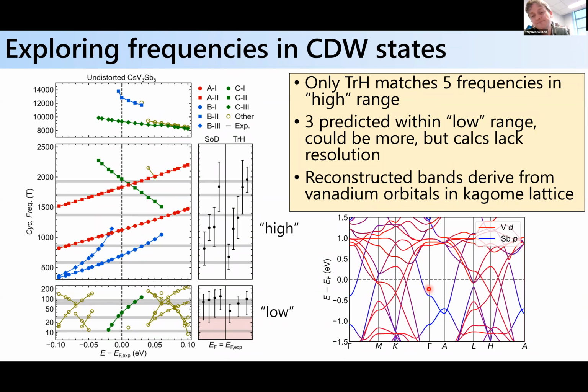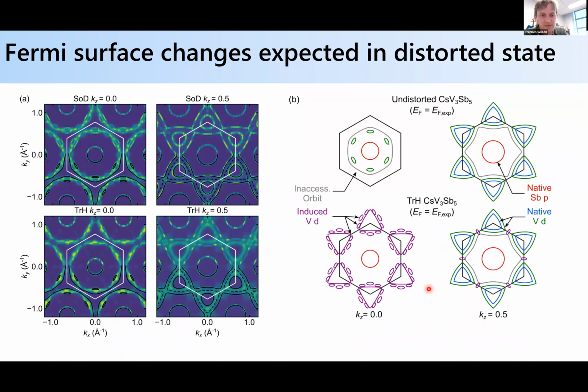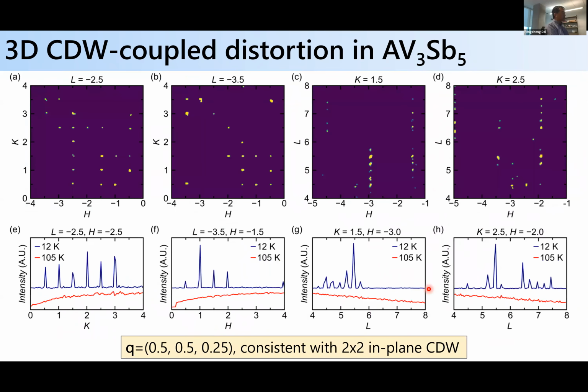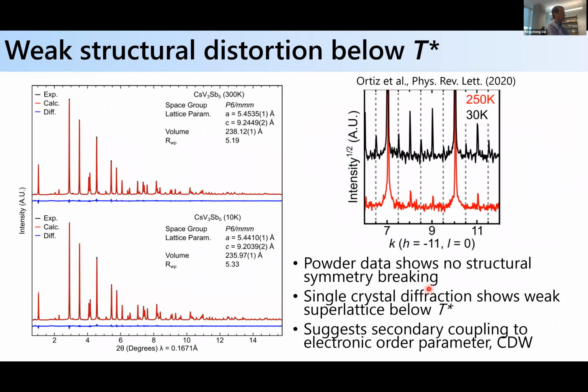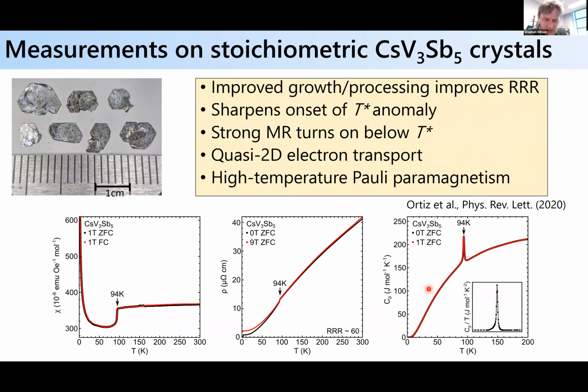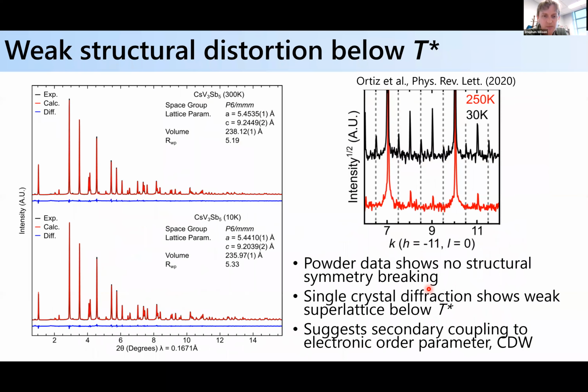We haven't identified it. Actually, Stephen, is your magnetization data consistent with the heat capacity data? Your heat capacity data seems to have an upturn at low temperature. You suggested that the susceptibility data seem to sink due to some sort of impurity, but your heat capacity data also shows a small upturn at lower temperature, right? So, let me see if I can find it in your heat capacity data. I briefly saw it. Yeah. Low temperature heat capacity. Okay. Yeah.